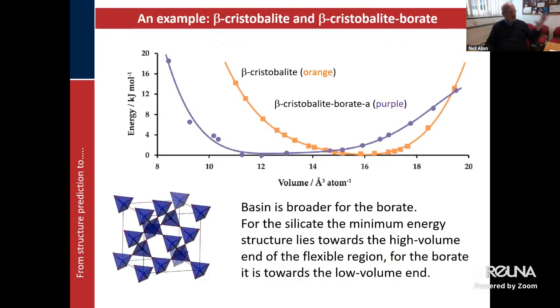And first of all, this is not a zeolite, but we tried taking beta cristobalite and turned that into the borate. And here are the energy versus volume curves we calculated a few years ago, first for the silicon and then the new boron equivalent. And you can see that the silicon-oxygen-silicon bond is flexible, but so is the boron-oxygen-boron, as we have seen. So the minimum energies, if we look at the purple curve, that's very broad.